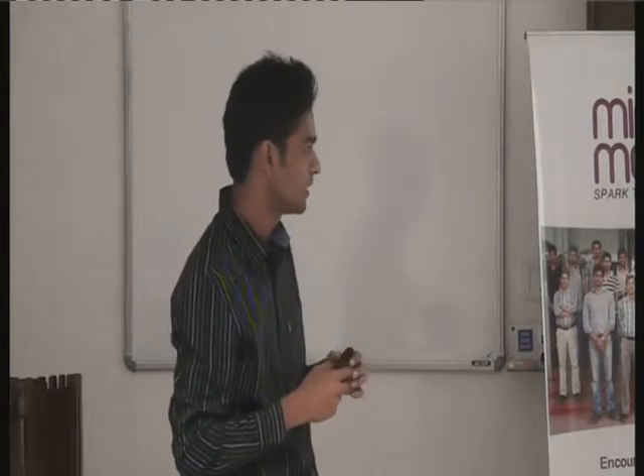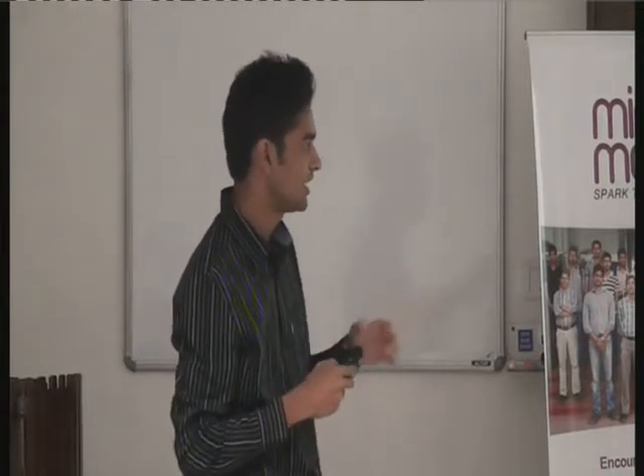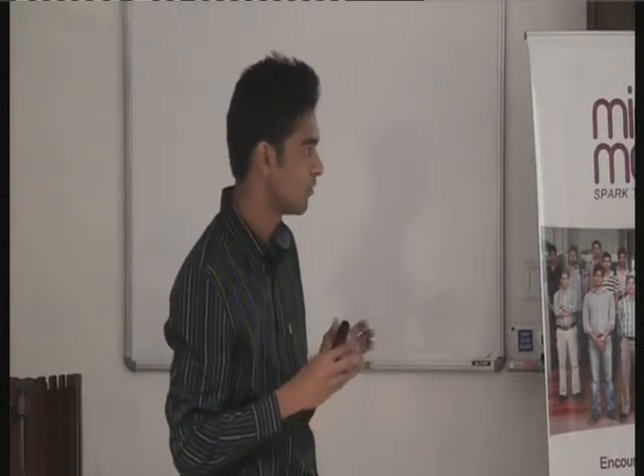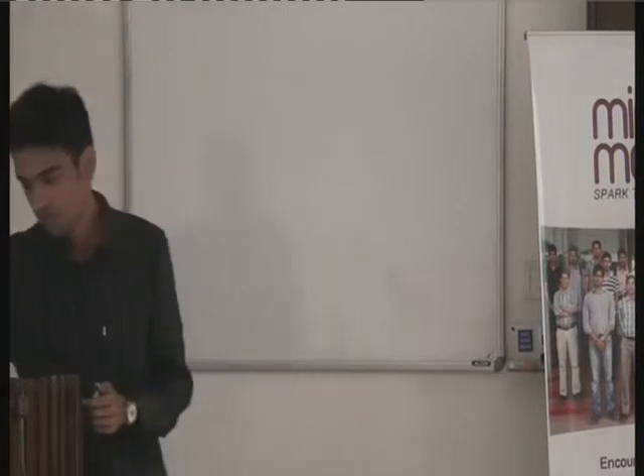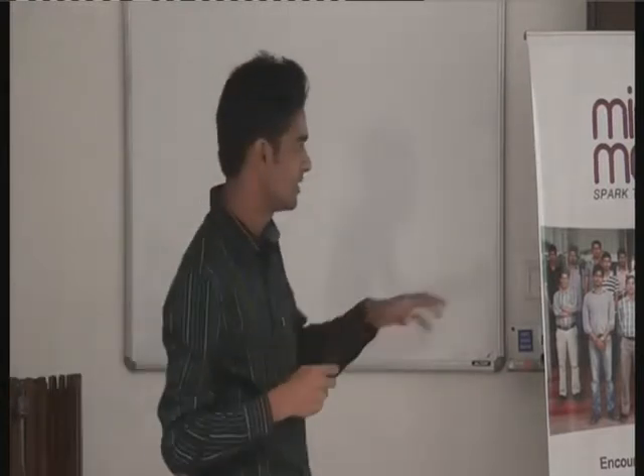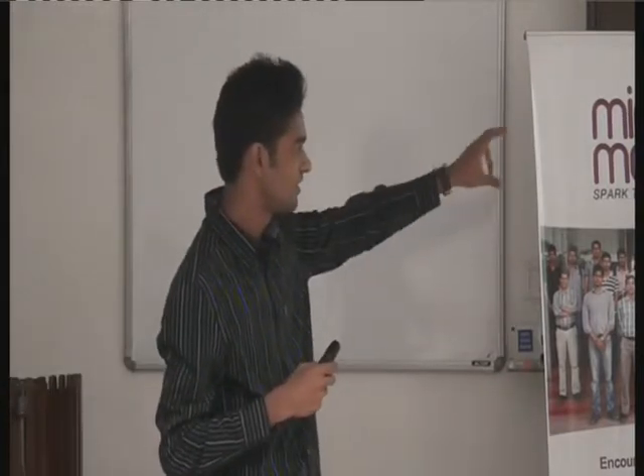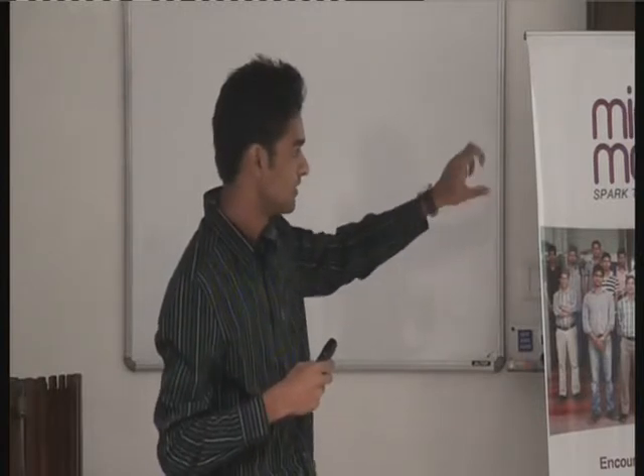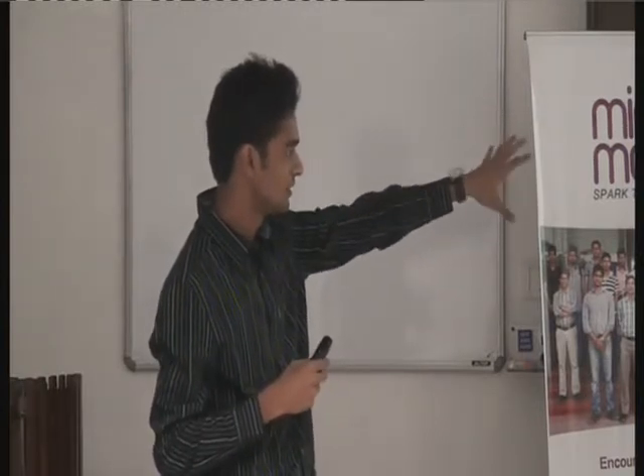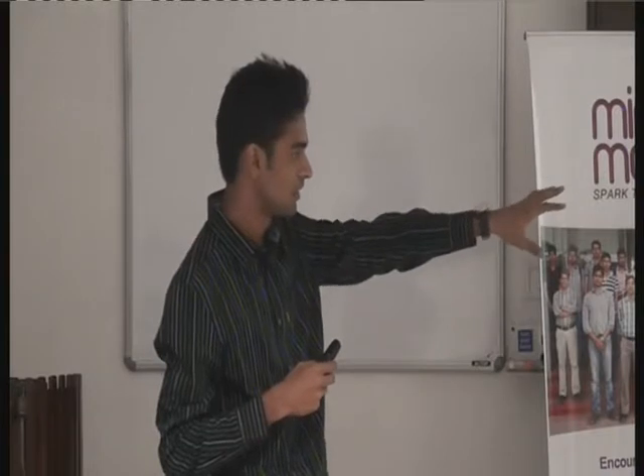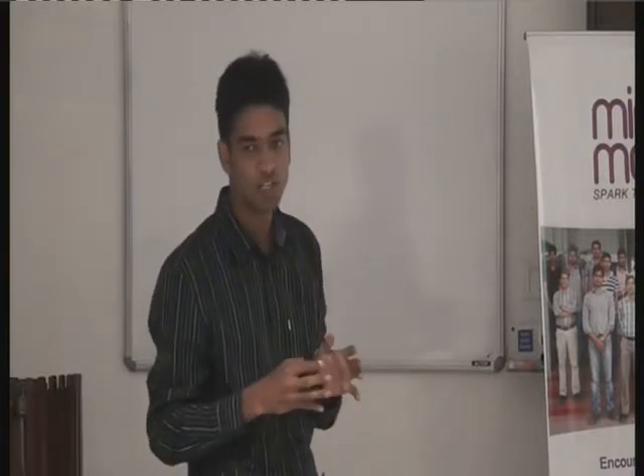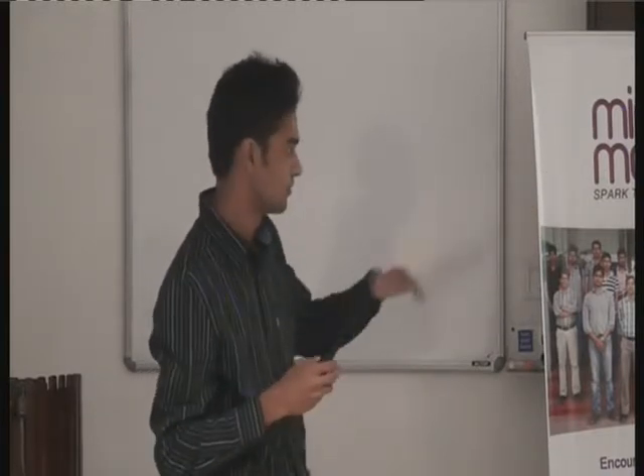At the current of 1 ampere, with an anodizing acid concentration of 190 gram per liter and an anodizing time of 40 minutes, I got the best result. Now this is the result I got. After anodizing, we can see in the upper part of both pictures that it becomes different, and after coloring I got this color, and the lower part shows the original without any anodizing or coloring.